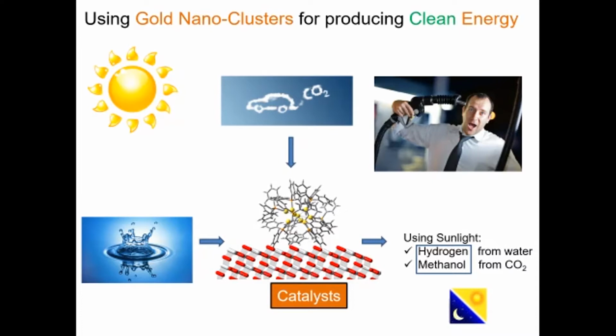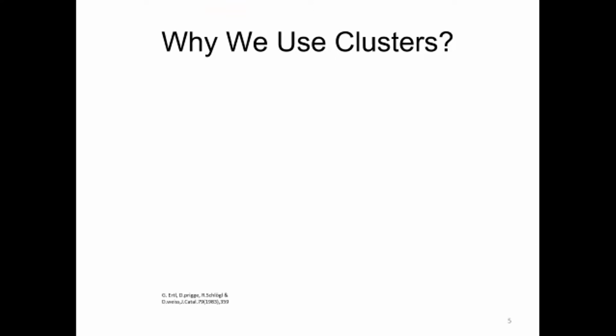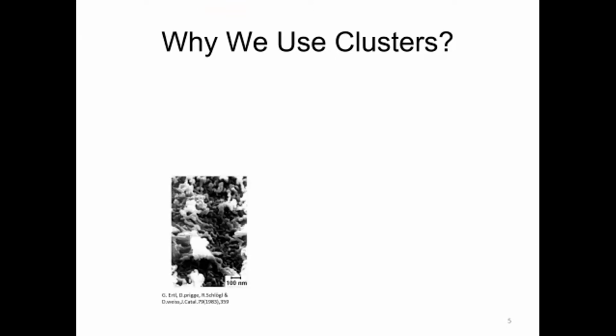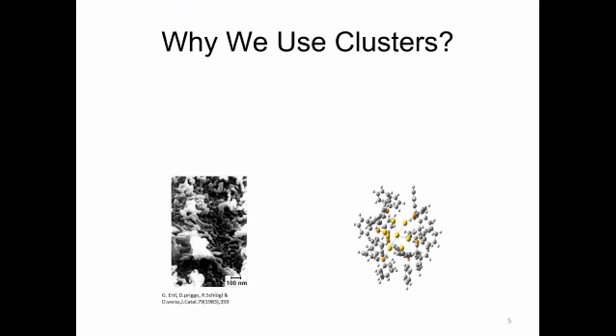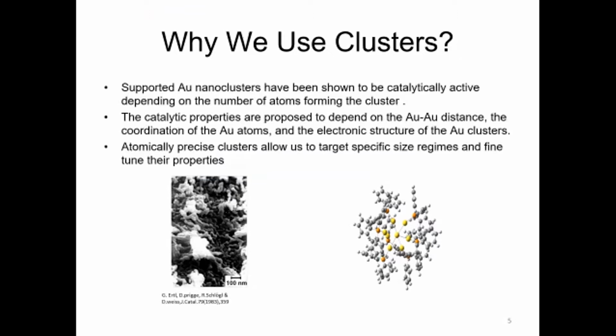Then why do we use a cluster? We already have an industrial catalyst, it's existing now. But the problem with this industrial catalyst is the huge waste of materials, and you don't know what the catalytic active area of this catalyst is. That's why we're changing to using the nanocluster, the precise nanocluster. And we support them on the metal oxide to increase the catalytic activity. And it has been proven in the literature.